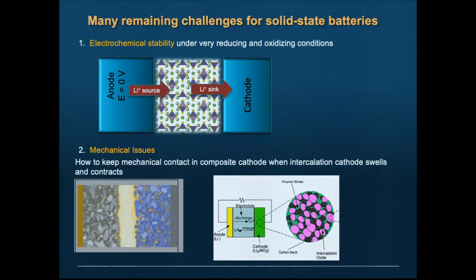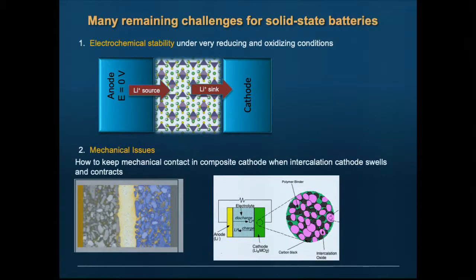But the biggest one is mechanical issues. So cathode materials swell and contract as they take up lithium. If you do this in a liquid electrolyte, the liquid just displaces and comes back. Now I'm going to have to make microstructures that are completely solid. Right? These are composite microstructures. They actually look like this. Let's say the blue thing is the active cathode, and then in between sits the conductor. But now you have to think of this as sort of a sintered or pressed composite, right? That's how this is going to look. And so this cathode is going to swell, contract, and you want to do this 1,000 times, right? You need 1,000 cycles. So the question is, how do you keep interfacial contact between these conductors and the cathode? So this is a major issue.